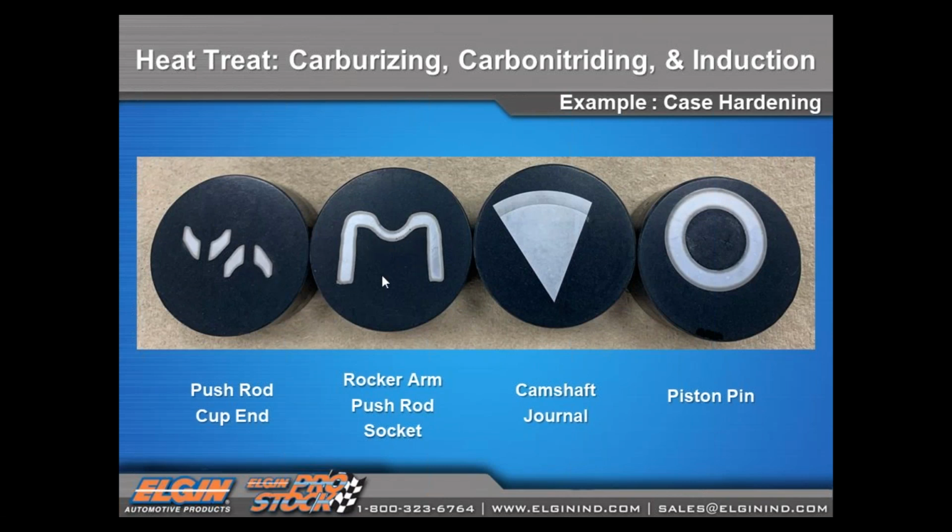Here's a cross section through a rocker arm, which everybody has seen, a stamped steel bucket type rocker arm, small block, big block Chevy. This is a cross section through the pushrod seat. If you've ever run a race engine or been a backyard mechanic that tries to race an engine that wasn't designed to do that, you're going to punch through your stamped steel rocker arms, usually once you go too high a spring pressure or too high RPM. This is where it'll fail. So if these were hardened all the way through, they would fail in 10% of the time that it takes to fail a part that's designed to wear for a long time and not punch through.